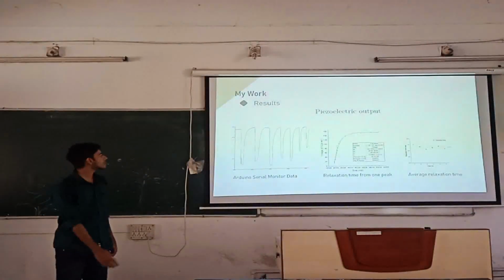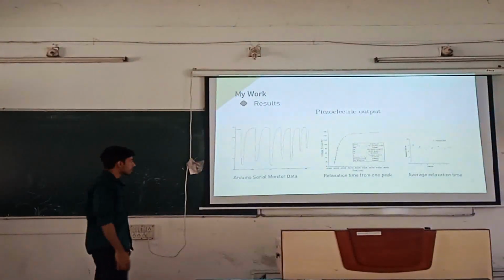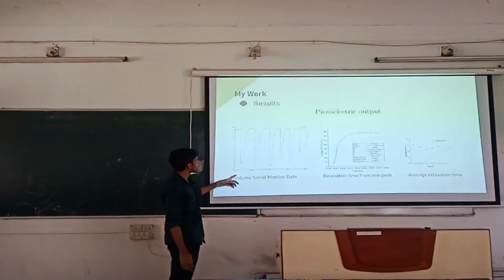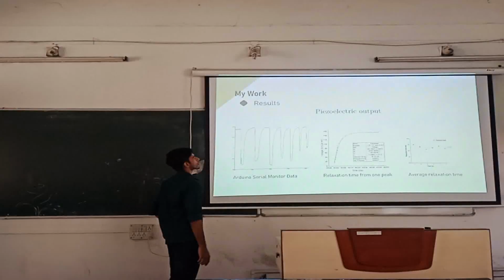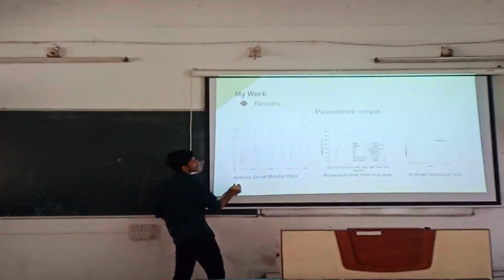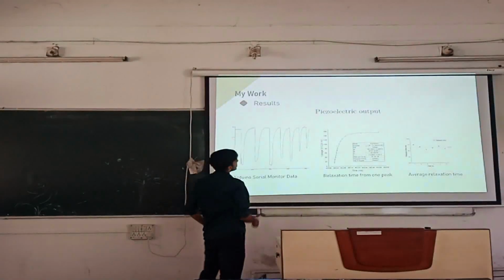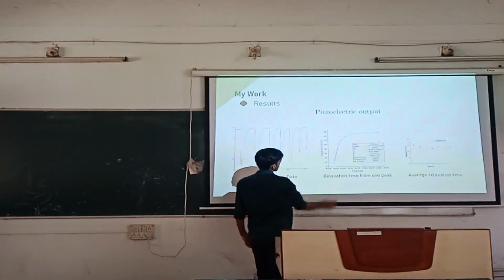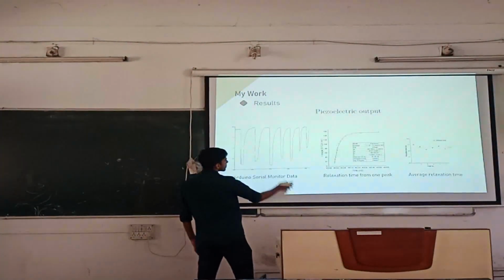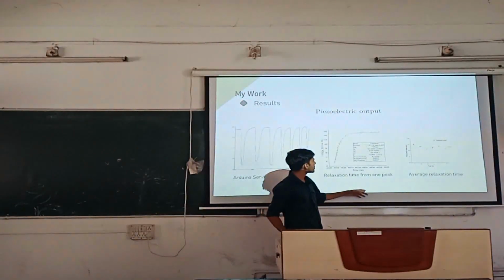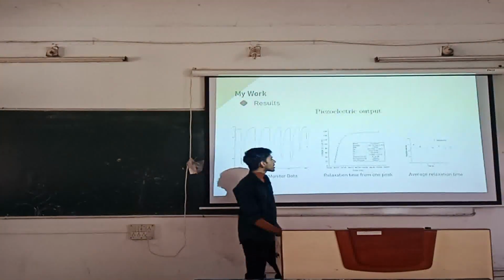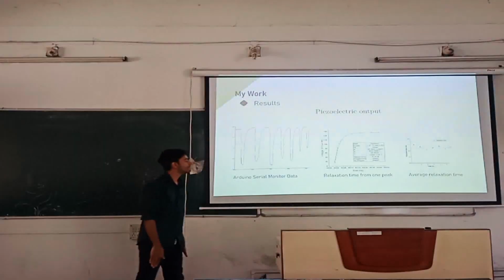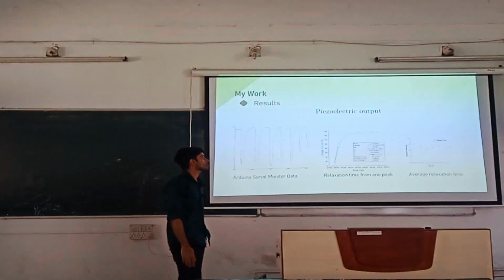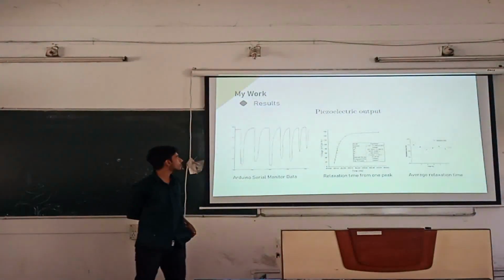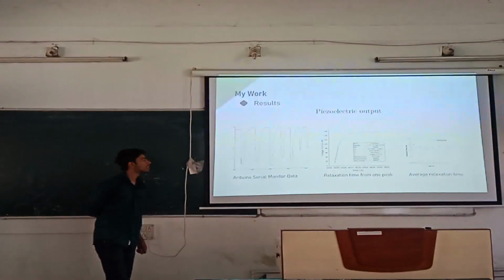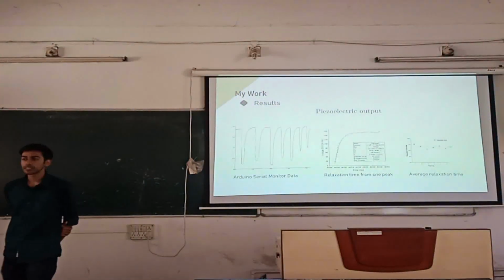So as you can see, this was the Arduino microcontroller's serial monitor data. We analyzed one peak, this one here, to see how much time it takes to saturate. We got 7.5 milliseconds as the characteristic time for saturation, the relaxation time, by taking the average for all.